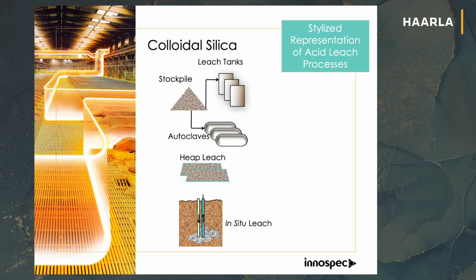So where are these actually coming from? You're going to see three slides, and the three slides are going to be very similar. The difference to show you, on the left-hand side of the slide, is where the silica comes in. It's the leaching process where it gets dissolved as you're trying to dissolve the targeted metal. And you've got the leach tanks, the autoclaves, the heap leach, which I've talked about, those three.